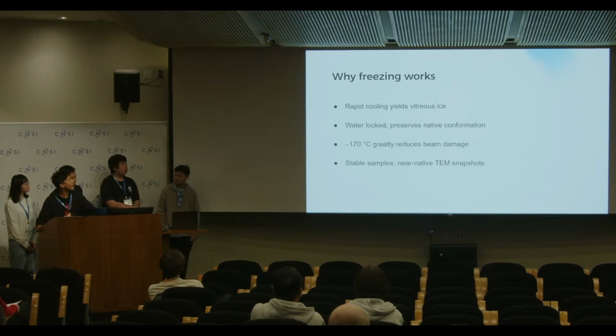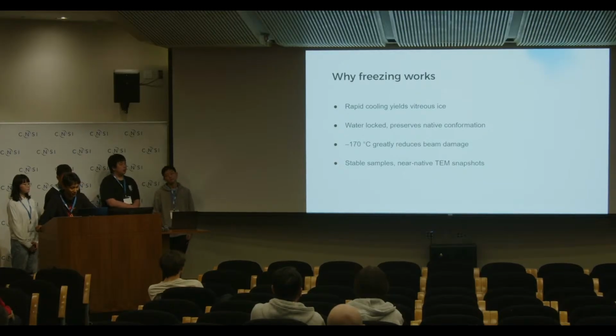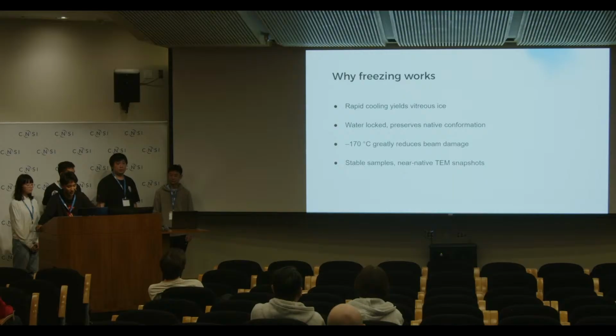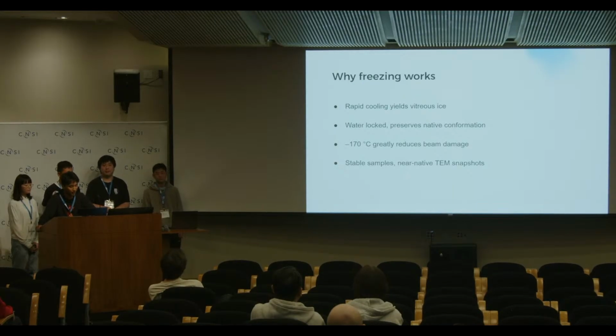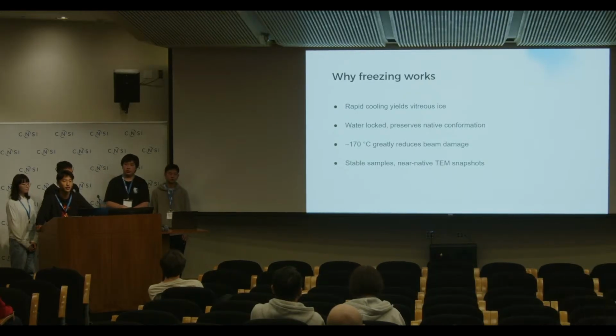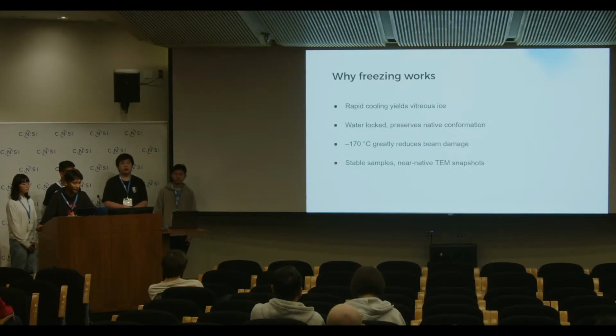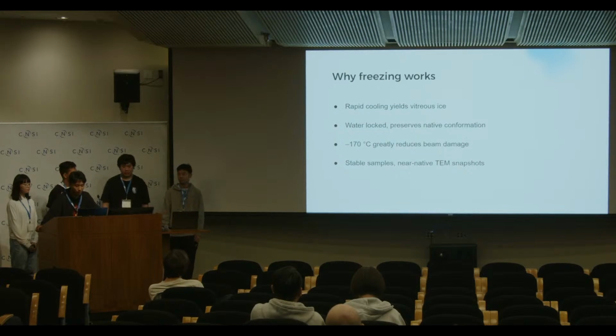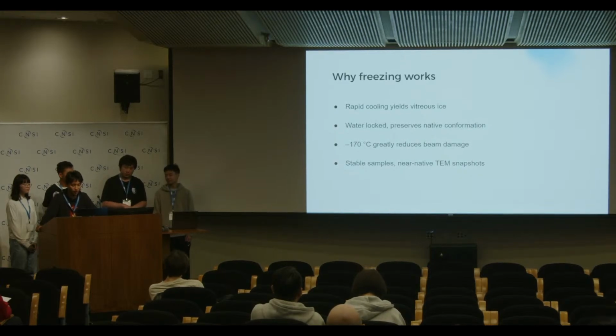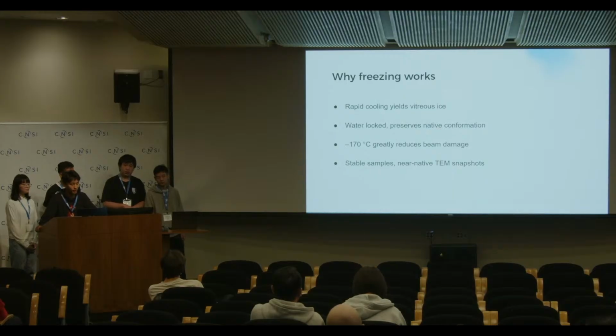So let's talk about why freezing works. Under these cryogenic conditions, the frozen hydrated sample is imaged in the transmission electron microscope. The glassy ice is transparent to electrons and preserves the molecular structures in a near native state. Because there are no large ice crystals, there are no structure distortions or lattice diffraction. Instead, the water appears as featureless glass that surrounds the particles.